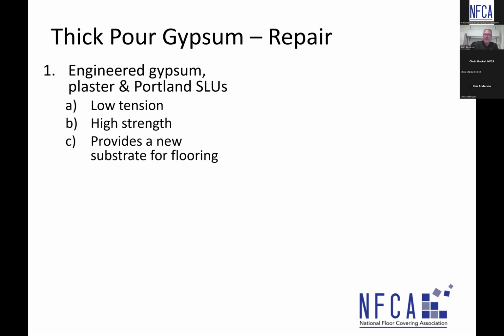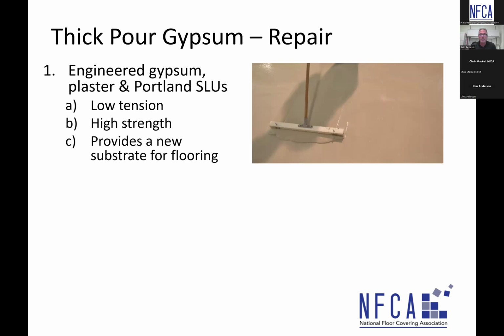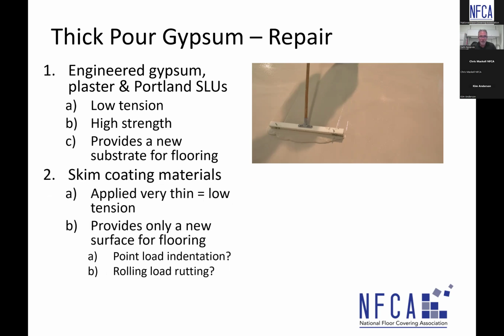So once we do our evaluations, there are repairs that are certainly doable out there from a self-leveling and a patching standpoint. There are engineered gypsum plaster Portland self-leveling products that are designed specifically to repair the thick pour gypsum materials. They're low tension materials. They're very high strength, compressive strengths up around 6,000, and it provides new substrate to put flooring down.